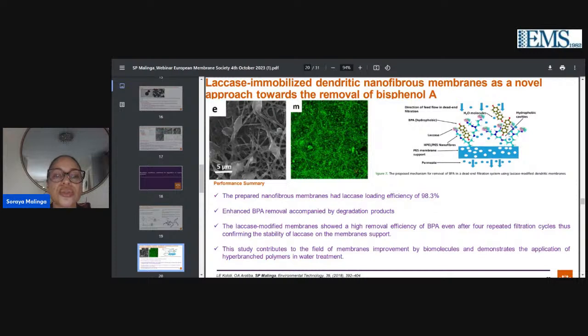What you do is that you soak your membrane in a dye. So this dye, when it interacts with light in the microscope, it fluoresces to green. So I guess depending on what dye you have used. So we were able to see that they were nicely spread or dispersed within our membranes, and then we exposed them to bisphenol A, and we were able to get quite interesting results as well.